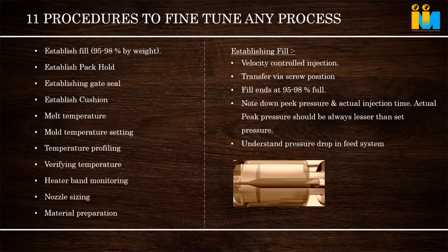And next is material preparation. Already discussed, preheating is based on the raw material specification. Overheating also results in volatile additives escaping out of the raw material. Then molding problems, ejection problems, sticking and flow problems can also come. Multiple problems can come. So based on that, preheating has to be done for higher grade engineering specialty plastics. Highly hygroscopic material has to be dried with a dehumidifier.